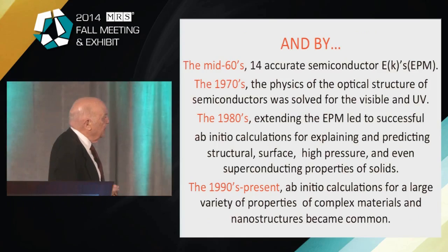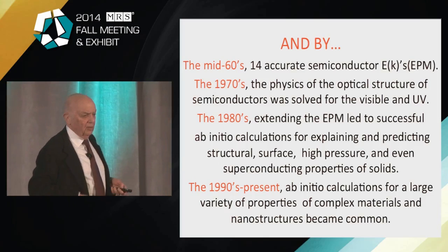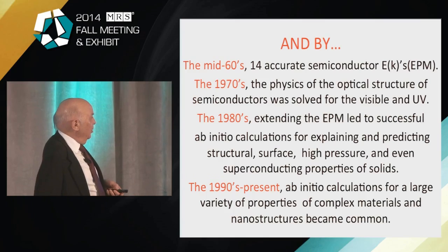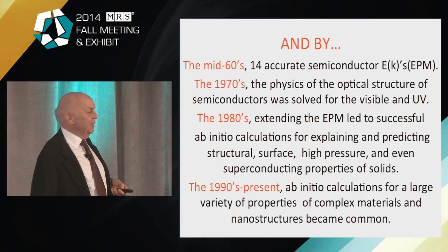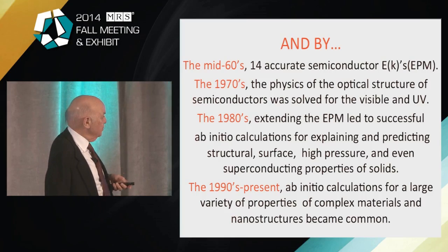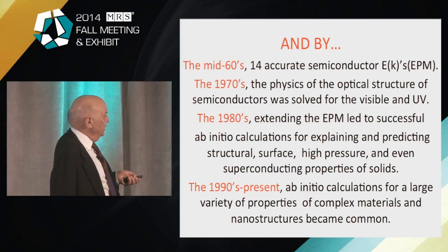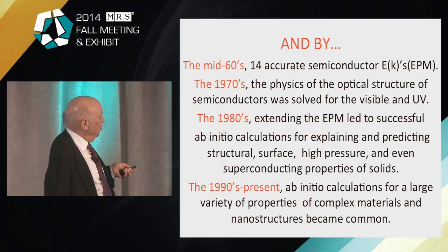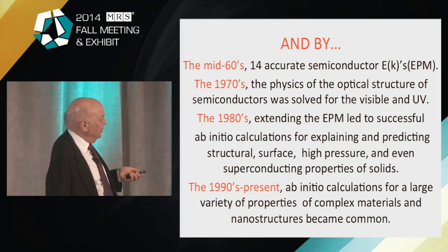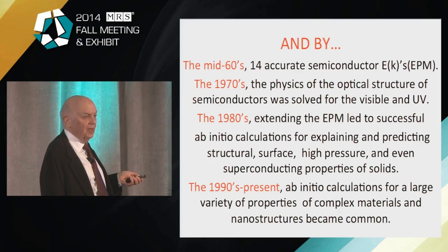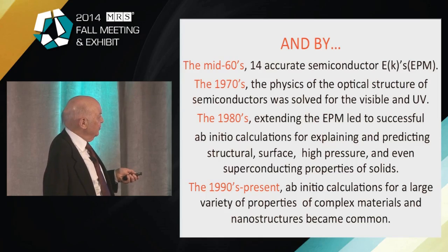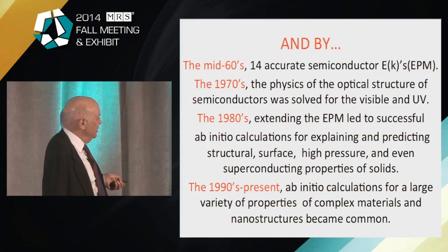So, in the mid-60s, we were able to compute the electronic band structure of 14 semiconductors at a period where people didn't know any, just because we were able to analyze the optical properties. And in the 70s, the physics of the optical structure of semiconductors was solved, and in the 80s, people extended the methods that were used in the 60s to do so-called ab initio calculations. EPM stands for empirical pseudopotential method. It means that we take in 3 parameters from the optical data, and can explain the optical spectrum. Ab initio means that we actually can start with just the knowledge of the atoms and calculate all the properties of the solid.